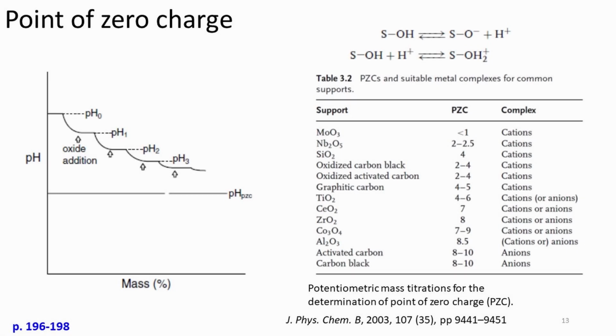To achieve strong electrostatic adsorption over a catalyst support, attention must be paid to achieving the optimal value of pH. The dramatic effect of the catalyst support surface on solution pH was first demonstrated in the method called mass titration. If a sufficient amount of oxide is placed into solution, the pH arrives at the point of zero charge for this oxide, at which point no driving force for proton transfer exists.